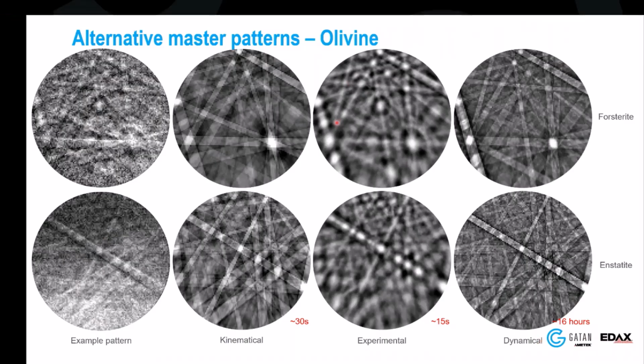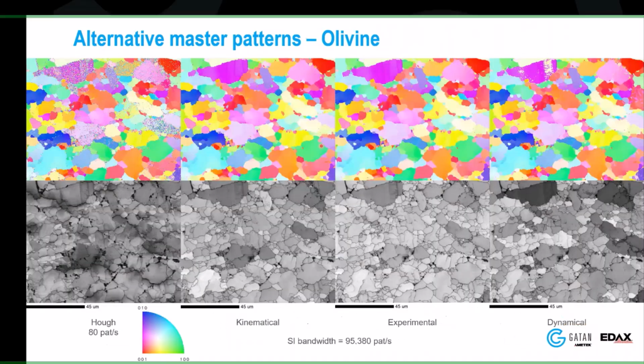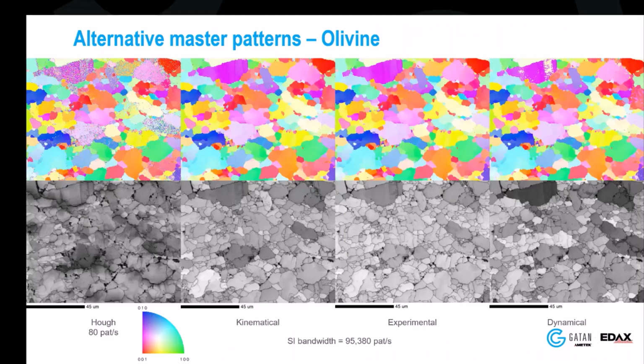And these experimental master patterns work very, very well. Here's an example of the Hough having trouble with some orientations in olivine, where running spherical indexing is pretty fast. Again, here you can see it goes relatively fast on this computer. This is controlled by your GPU, by the way. It's one of those things we always talk about, how fast it goes, but the more computing power you throw in, of course, it's going to be faster.